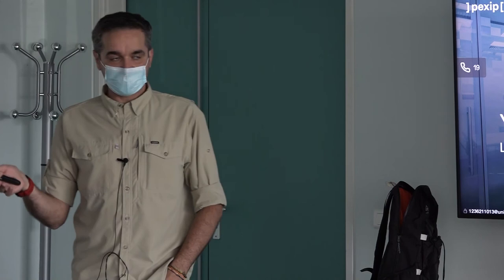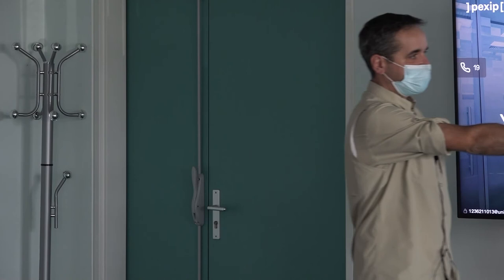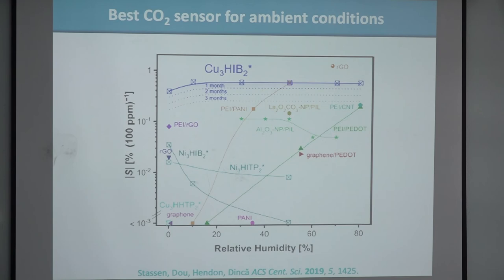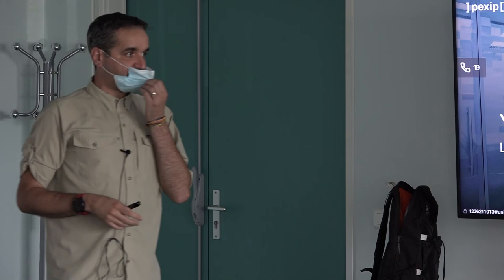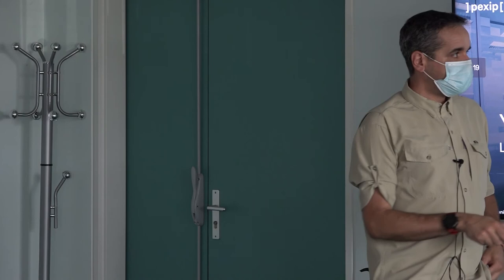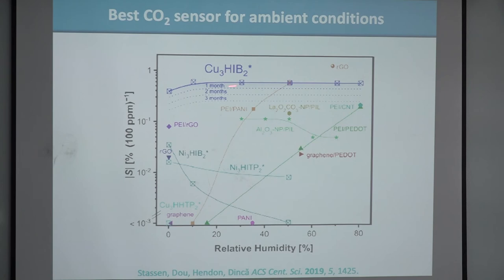This material literally looks like graphite except it's porous and has a different composition. We can make pencils out of a MOF, draw with it between two electrodes, and use it for chemo-resistive sensors. For CO2 detection, detecting CO2 at atmospheric levels is really difficult — currently done with mass spec or infrared — but if you want a quantitative CO2 sensor in every room, that's very hard. Humidity kills many approaches, but our material works in the 400 to 2,000 ppm range, which is unfortunately where we are now with CO2.